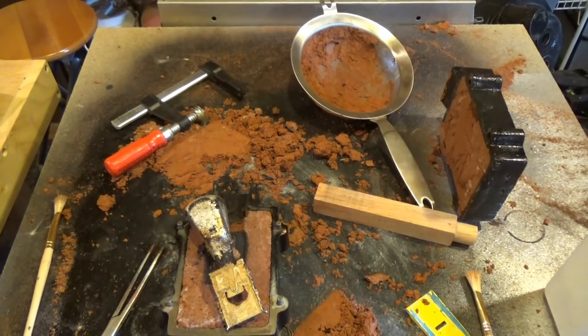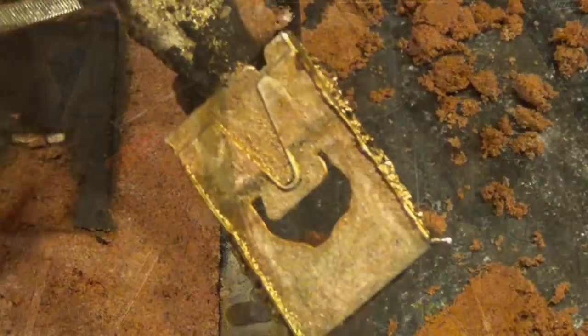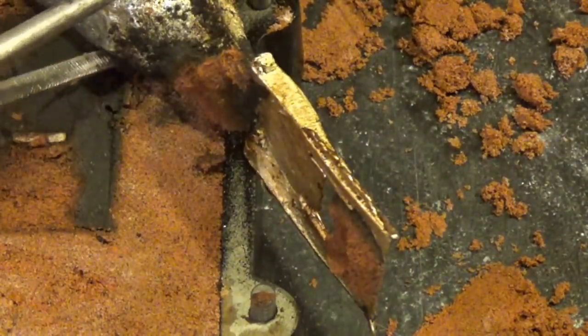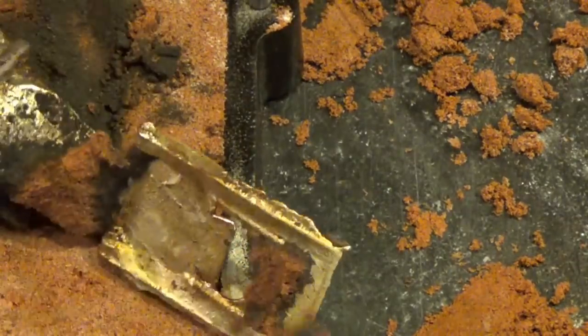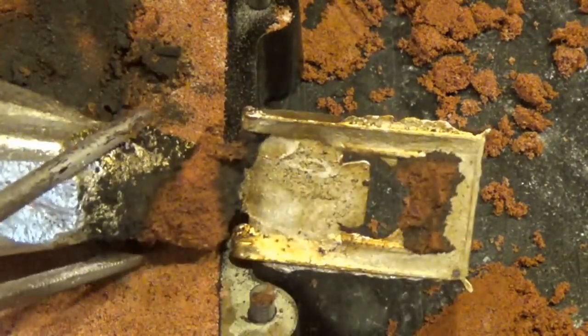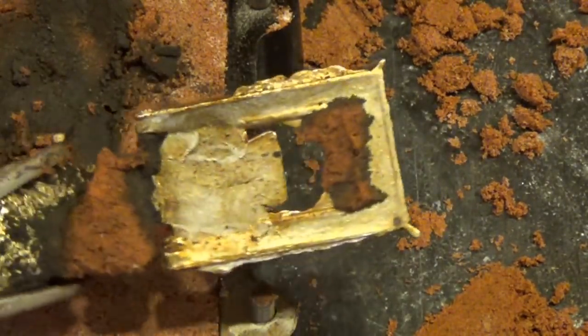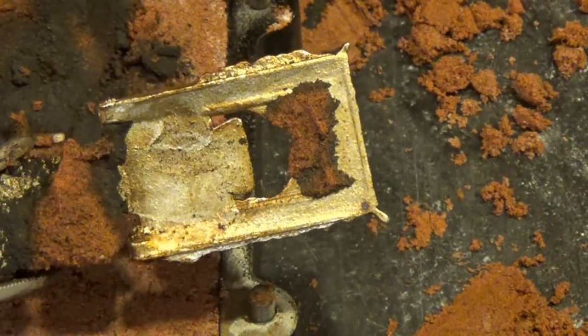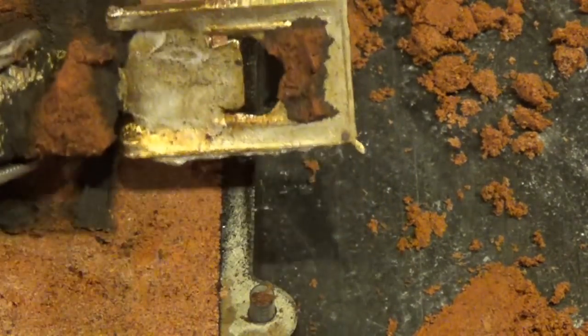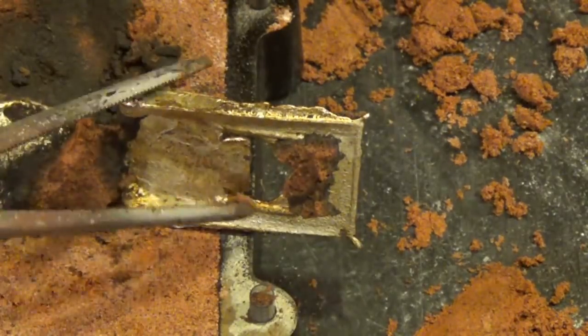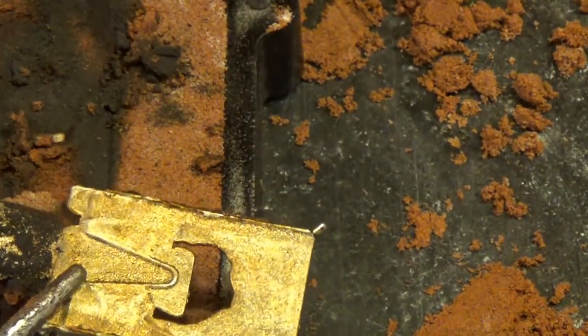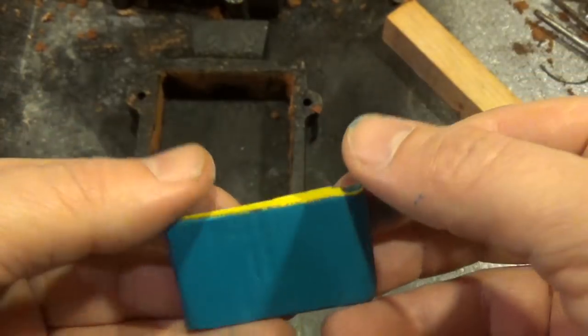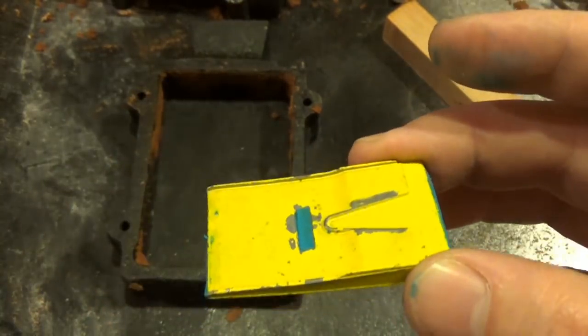This is mostly due to the part being so thin. The mold cools the metal off in the thin areas as there's just not enough molten metal to keep the aluminum liquid. This problem is going to keep showing up for me on this part. I tried modifying the mold in several different ways, but was never able to get a good cast. So, at my wit's end, I decided to fix the problem by making changes to the part. The change for this part is very simple and involves using more modeling clay to fill in the back of the part to give it more thickness.